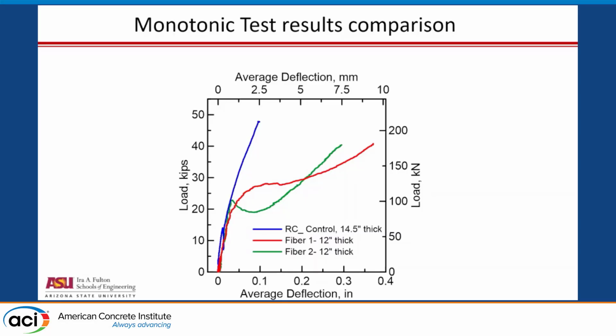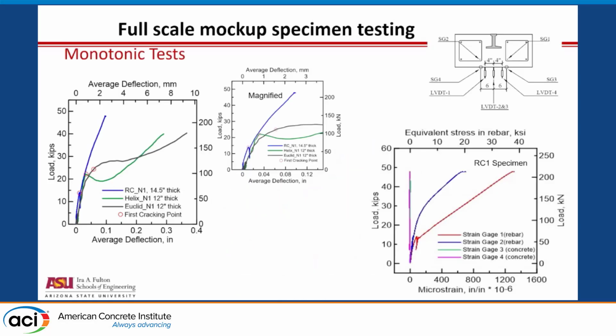And the first cracking is actually extended, even though it's a thinner section, so there is a stiffness effect because of the depth, but then you go up to about 25, then once the fiber cracks, your crack can open up to about 0.2 inch opening or 5 millimeter opening, which can be easily repaired within a slab on ground from routine maintenance, maybe every 10 years. And that would put us about 3 times the capacity that we would need.